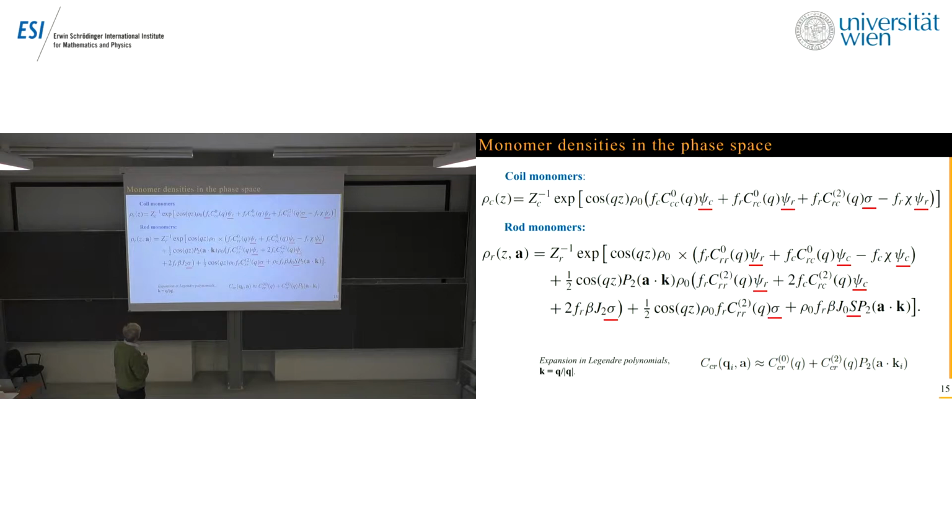So now we can also do the last bit. We expand our direct correlation functions, which depend on density-density correlation functions, which depend on the orientation. So we can expand them in Legendre polynomials, again taking only the first interesting term, which contains the second Legendre polynomial, because our interaction is limited to the P2 term in the Maier-Saupe.